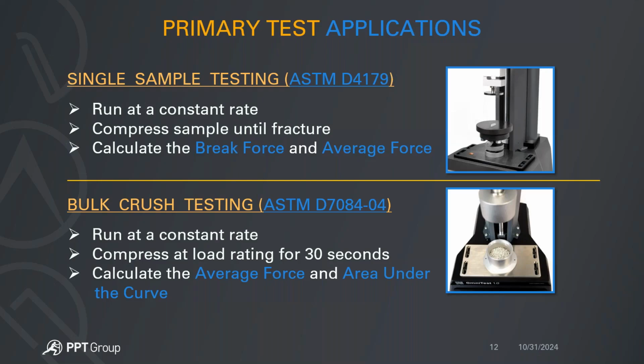And then there is bulk crush testing according to ASTM D7084-04. Similarly, instead of testing a single pellet this time, you measure and test a bulk quantity in a cup or circulometer or pod that will hold that quantity, and then you bring down either a compression plate or a plunger, and then apply a known force at a constant rate for 30 seconds. And then at the end of the test, we'll calculate the average force and also the energy, or the area under the curve.